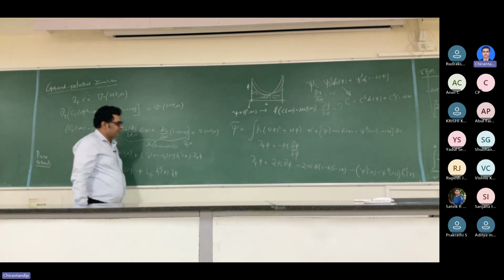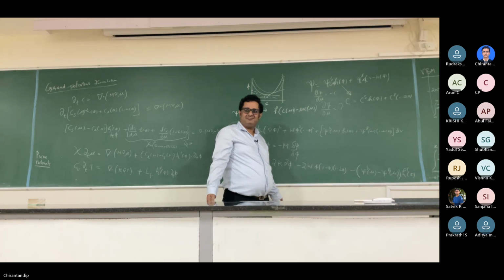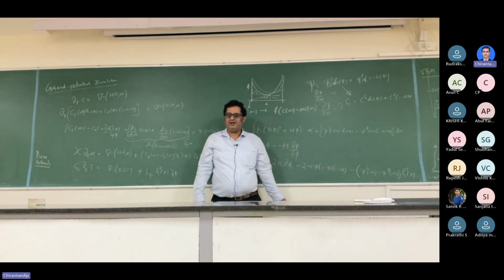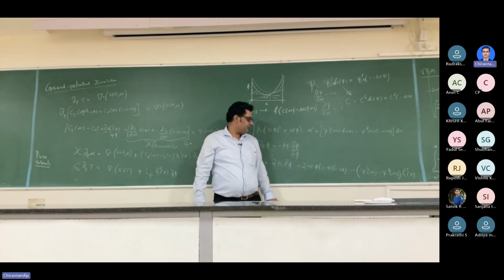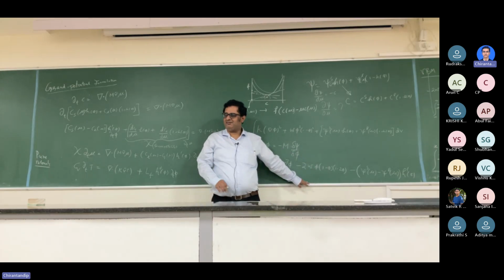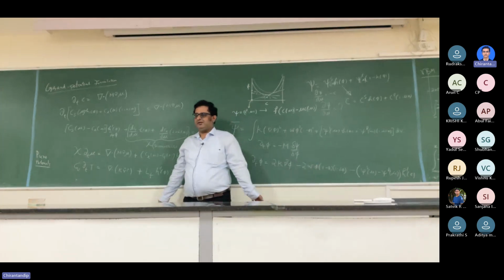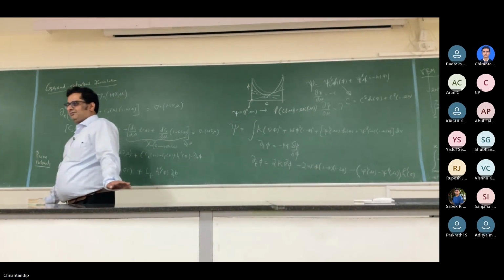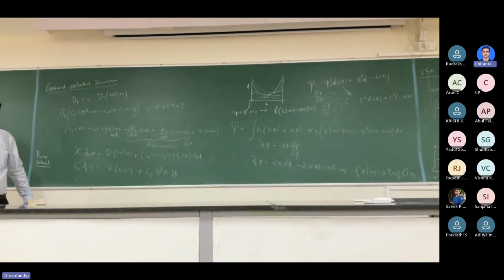Not only that, your equations are exactly the same, and the derivation is much simpler. Okay, remember the KKS model? You have to bring in 2 or 3 theorems together to get the derivation done. Here, it is a one-step derivation, just as for the pure materials. Right? And that's the beauty of it. It unifies everything. It unifies everything in the sense that once you have identified the thermodynamic driving force with the right variable, you can essentially formulate any history. Right?